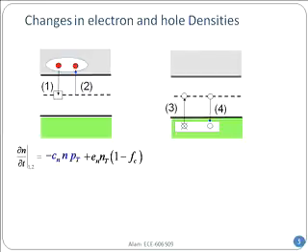that between the valence band and the trap, you can write the same thing. 3 and 4, I'm focusing on the number of holes this time. Again, Cp, P and N sub T. P is the number of holes, N sub T is whenever they are occupied, because holes are captured by occupied traps. Remember, that's when it has a large cross section in the last class. And correspondingly, it has the emission probability.